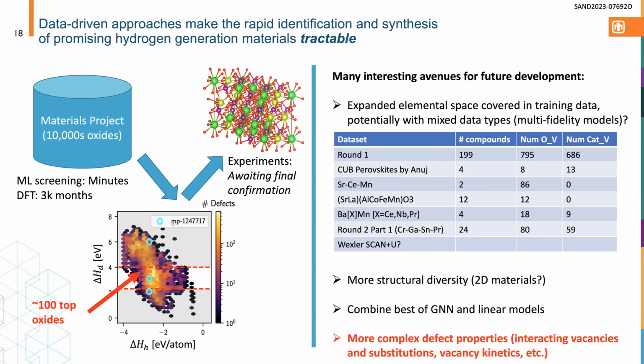And I'm also interested in seeing if there are ways to do multi-fidelity models. So we could use Rob's calculations with SCAN plus U and integrate that with our DFT data, which was calculated with GGA plus U, for example. Look at more structural diversity, and then also combine the best of both worlds. So I mentioned GNN has advantages and disadvantages. The linear models, for example, that Rob has worked on have advantages and disadvantages. So if we can marry the best of both worlds, it would be really cool to see how much more progress we can make.